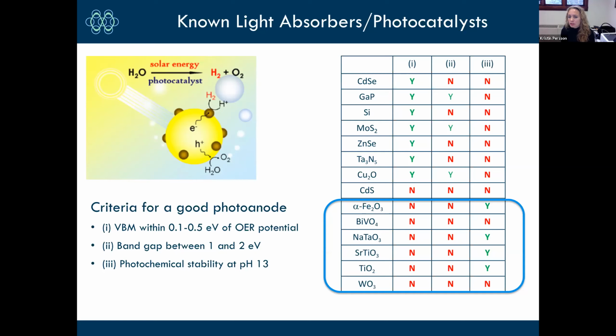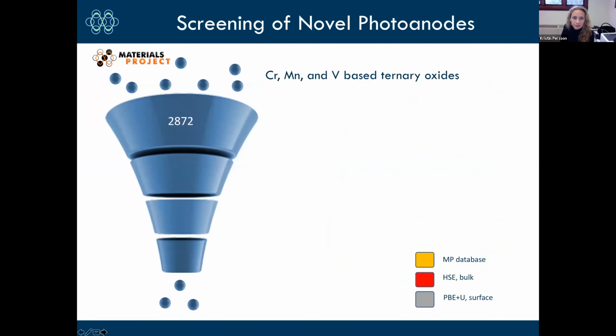So then we look towards the oxides, and the oxides are more stable under these conditions. So they do okay on criterion number 3, but not so well on criteria number 1 and 2. So what we were interested in seeing is whether the Materials Project, with all its data and its ability to calculate the electronic structure of materials, could identify specific oxides that really have those unique properties of the right band alignment and the right band gap for this application.